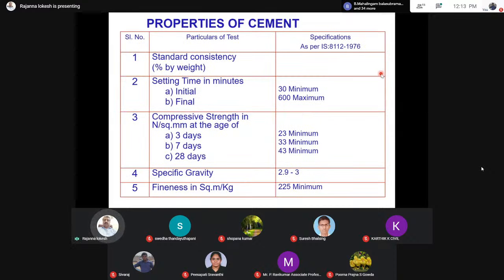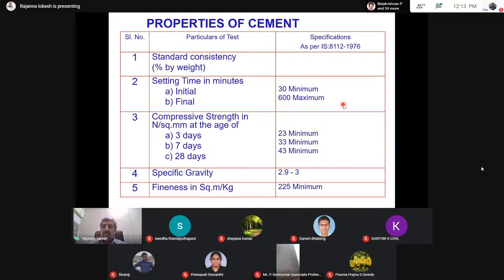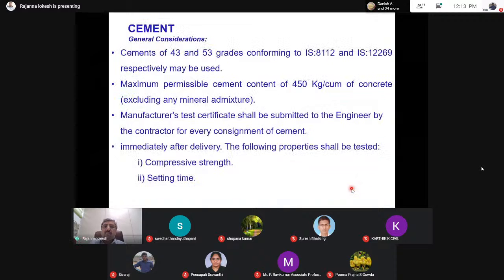So the properties of cement shall be: initial setting time should be 30 minutes, final setting time shall be 600 minutes. Compressive strength of cement for 3 days shall be 23 MPa, whereas for 28 days it shall be 43 MPa. Specific gravity shall be 2.9 to 3, whereas fineness shall be 225 square meter per kg minimum requirement. As I told, generally we can use 43 grade and 53 grade cement.